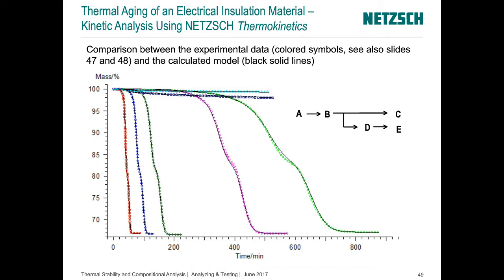The result of such a kinetic evaluation you can see here. The colored symbols are the original measured data, and the black curves are the calculated curves based on the model we see on the right side. The best model found was A to B and B to C, but this was also branched from B to D and from D to E. So this is a formal kinetics approach, and behind such a reaction from A to B, different mechanisms can be found.